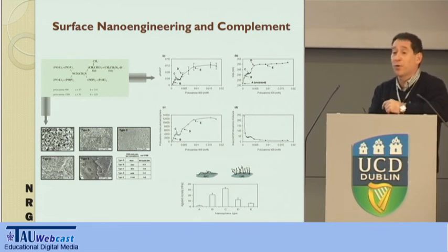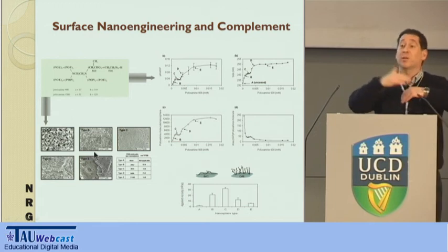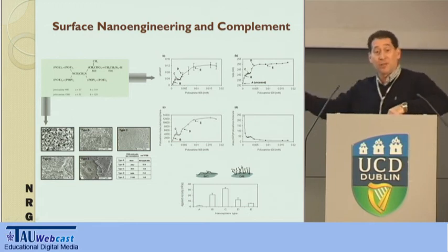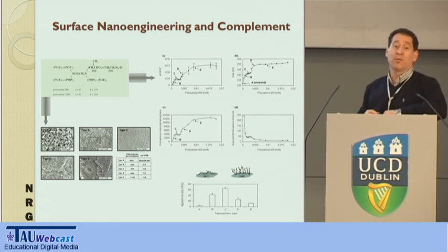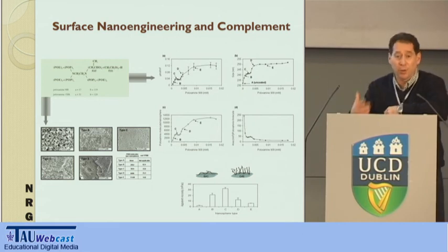I don't have the data to show you here, but again, as a nanorheology, and in terms of the scanning electron microscopy, you can see that you have the aggregation of the particles as you come to the first plateau. You are making hexagonal phases, and as you go on top, you're actually trying to stack that because of the electrostatic repulsion. We also characterize the polymers themselves in terms of the polydispersity and the purity and so on.